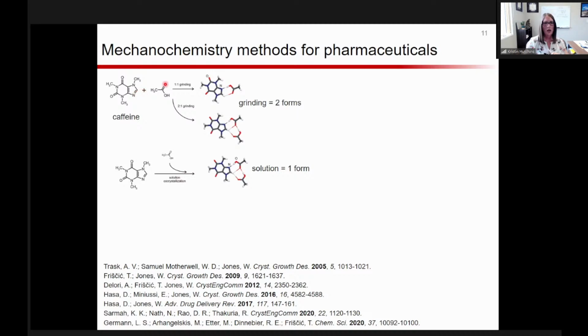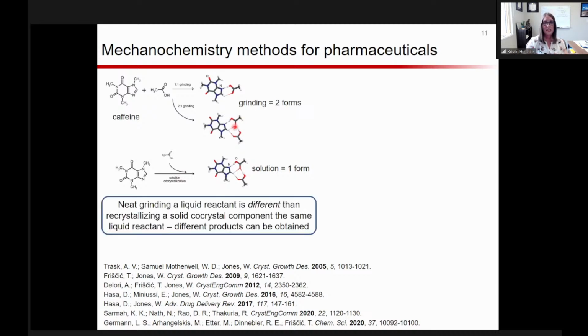And so when they did a 1-to-1 ratio by grinding, they isolated one form, but a 2-to-1 ratio gave them a second form. And then when they actually did this in solution, where they dissolved caffeine in acetic acid, they were actually able to isolate this second form that they got by their grinding method, but they weren't able to isolate this top form. So I've sort of paraphrased here in this box the takeaway from that, which is similar to a case you're going to see from our lab in just a little bit.